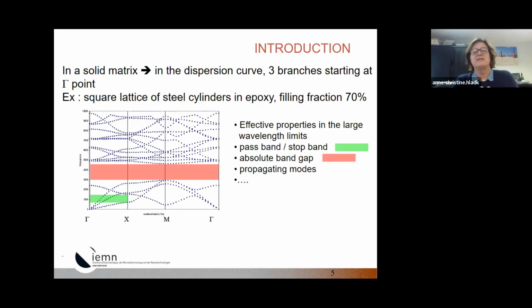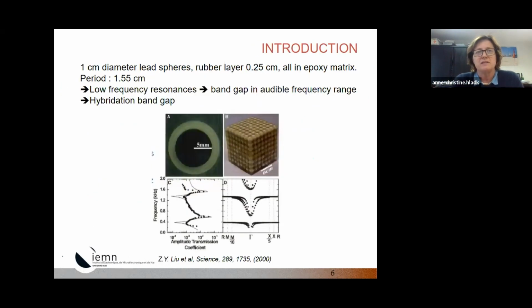In the previous cases, the matrix was fluid, air or water, and in that case, you have only one branch starting from the origin. In the case of a solid matrix, like in this one, a square lattice of steel cylinders in epoxy, then starting from zero, you have three branches: one for the longitudinal wave and two for the pseudo-transverse waves. But it is the same. You draw the dispersion curve and then you try to identify band gaps in a specific propagation direction, the green color, or for all the directions, the pink color.